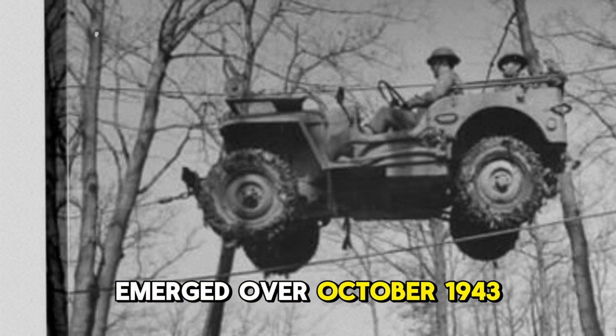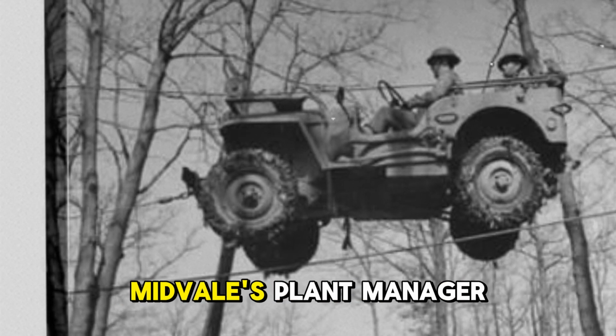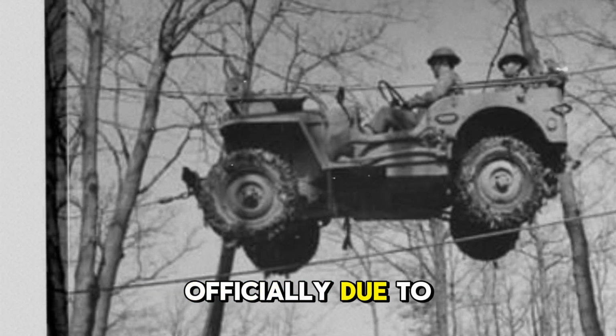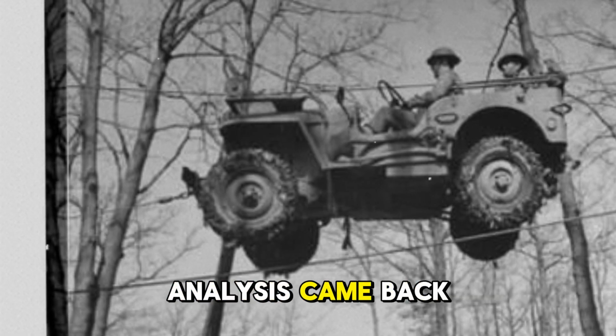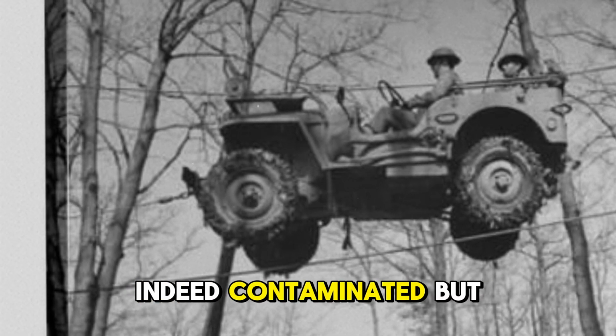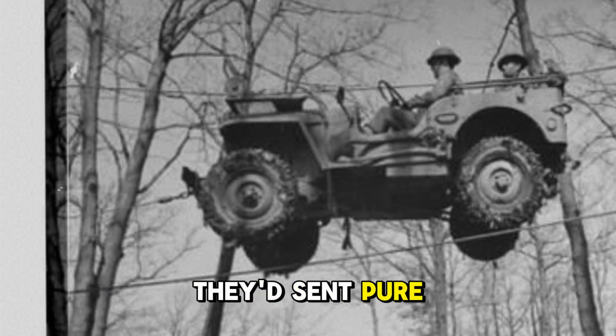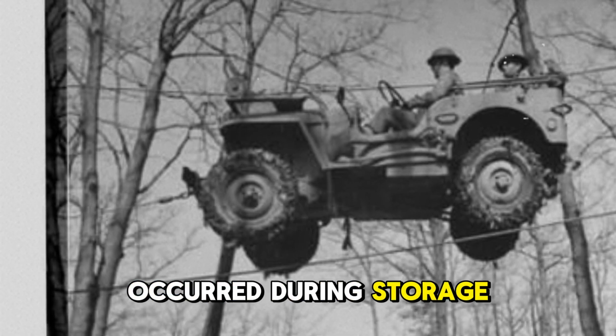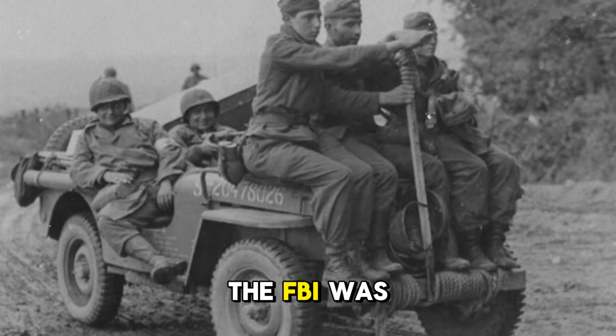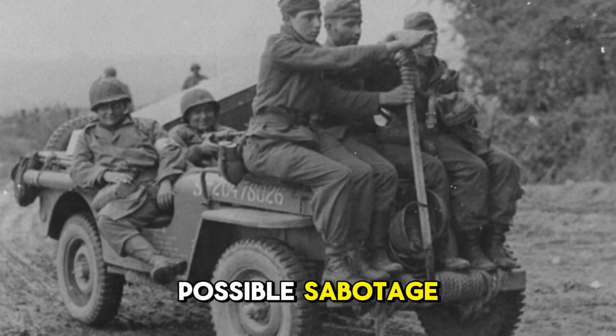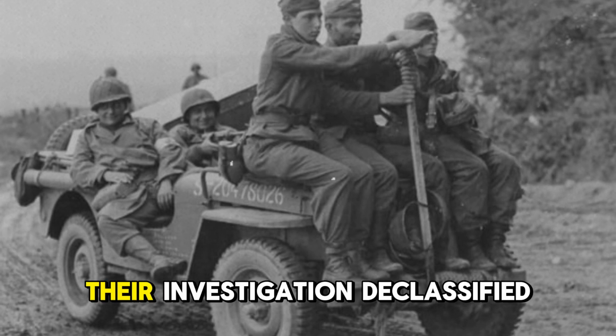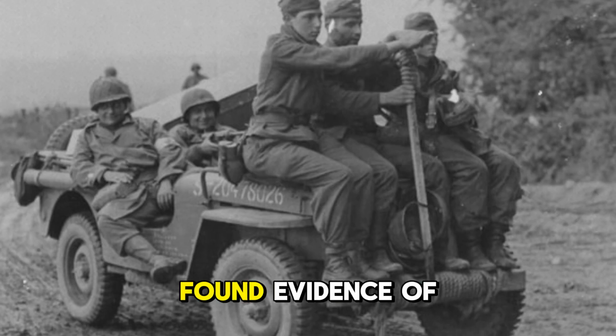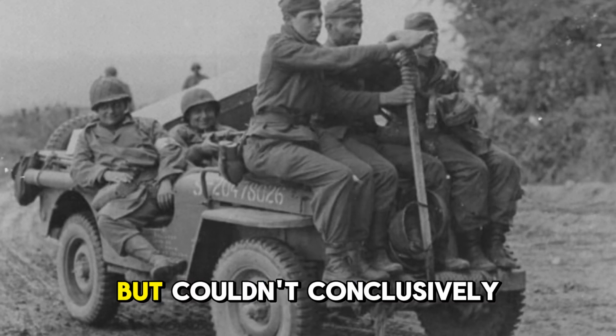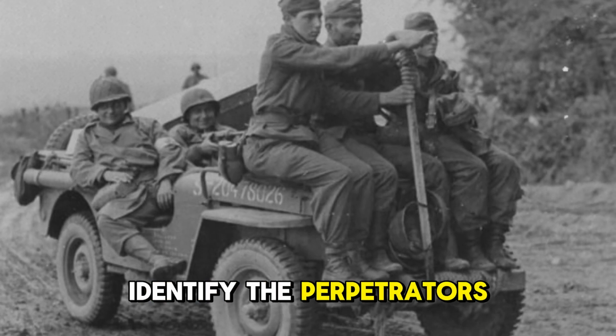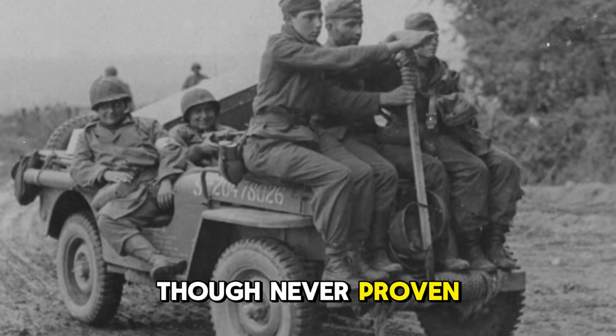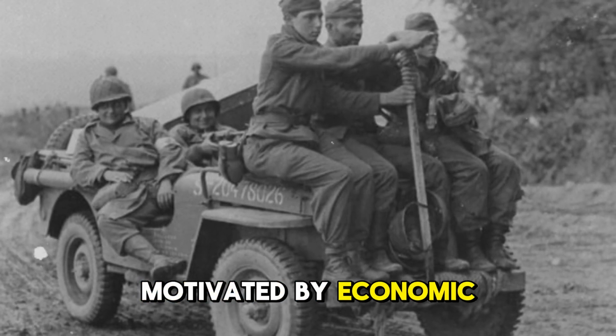The picture that emerged over October 1943 was increasingly suspicious. Midvale's plant manager was replaced suddenly, officially due to health reasons. The independent laboratory analysis came back, showing the molybdenum shipment was indeed contaminated. But Climax Molybdenum insisted they'd sent pure material and suggested contamination occurred during storage or handling at Midvale. The FBI was quietly brought in to investigate possible sabotage, given that this involved war production. Their investigation, declassified decades later, found evidence of at least 2 instances of deliberate tampering, but couldn't conclusively identify the perpetrators. The most likely explanation, though never proven, was industrial sabotage motivated by economic competition.